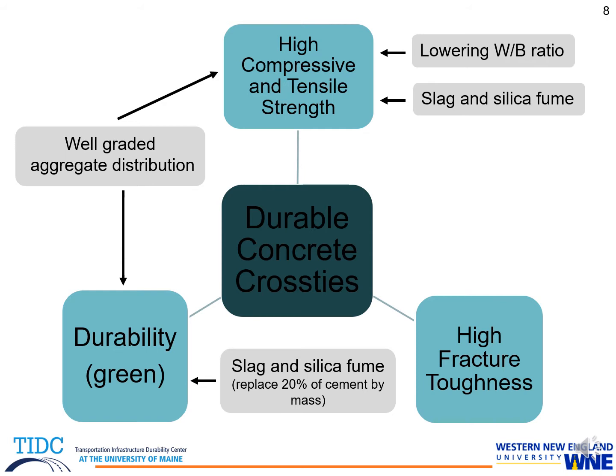as durability. To get high strengths, we've focused on lowering the water to binder ratio, adding slag and silica fume along with the cement, and creating a well-graded aggregate distribution. And the well-graded aggregate distribution also points to durability because it creates a dense concrete that's very smooth on the edge surface, so that helps with abrasion. Durability is also improved because of adding slag and silica fume due to their fineness. And it's also an environmentally friendly item because it replaces 20% of our cement by mass.